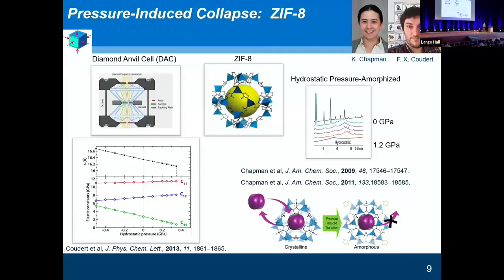Right, that's it for shear-induced collapse. So let's move on to hydrostatic pressure-induced amorphization. Right, we can shear things or we can just try and squeeze them. This is excellent work done by Karena Chapman way back in 2009, before we'd started thinking about this pressure amorphization. And what Karena did was use a diamond anvil cell. So two diamonds pointing into some solvent, your MOF, everyone's favorite MOF, ZIF-8, in the middle. And then when you squeeze the diamonds together, you apply pressure to the MOF system itself. Karena showed that actually at 1.2 gigapascals, that's not that high pressure, that's irreversible amorphization. Whatever you've done by squeezing that MOF, it's not coming back.